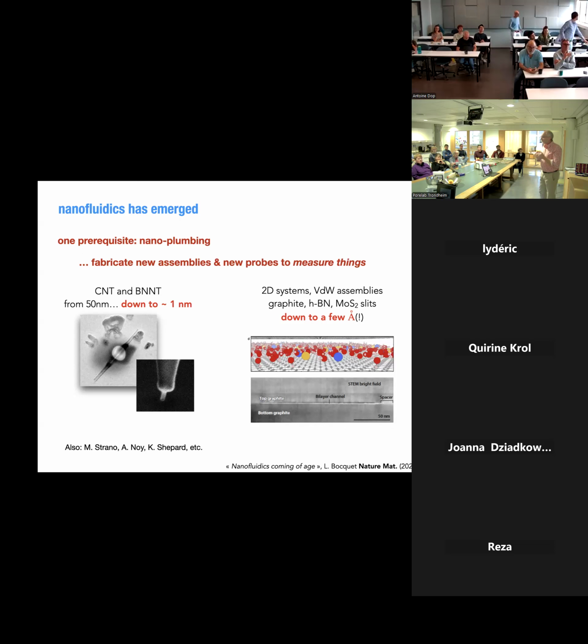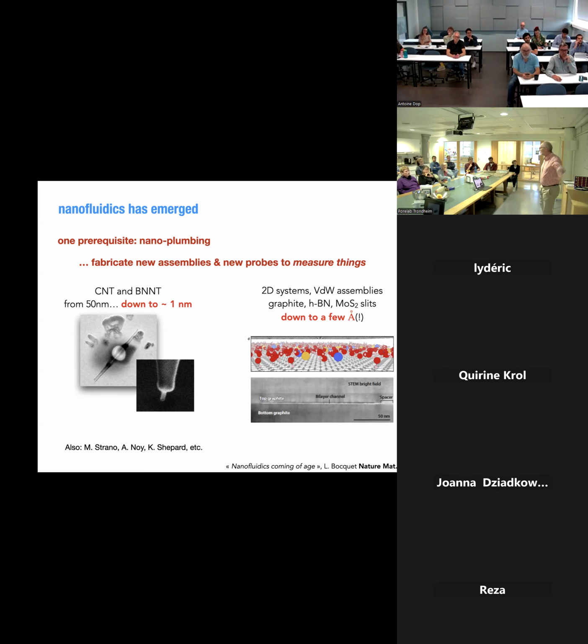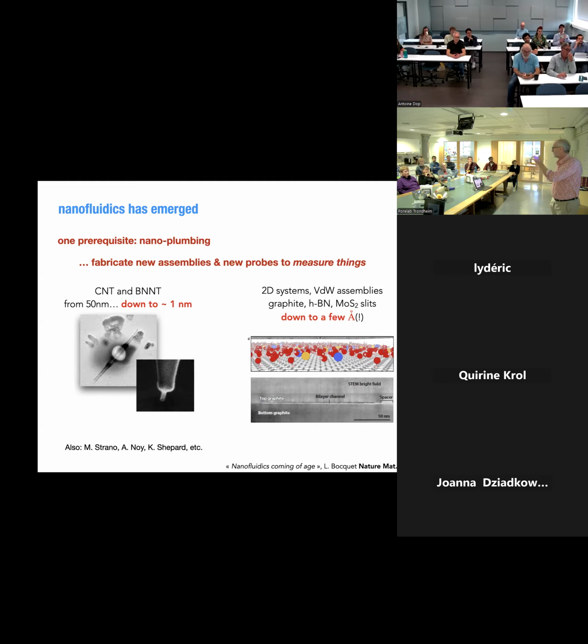and bottlenecks in this. So this domain really emerged when we started to be able to fabricate things. So basically, you need to do some plumbing at some point. And without plumbing, you can think of plenty of fancy phenomena, but you can't do anything. And actually, it happens that we strongly benefited from nanomaterials, so carbon nanotubes, boron nitride nanotubes, graphene, etc. Which I will tell you a bit more about. And not only us, all over the world there are a few groups which do that. And now it's possible to study transport of fluids and ions in carbon or boron nitride nanotubes down to 1 nanometer in diameter in a very controlled way.